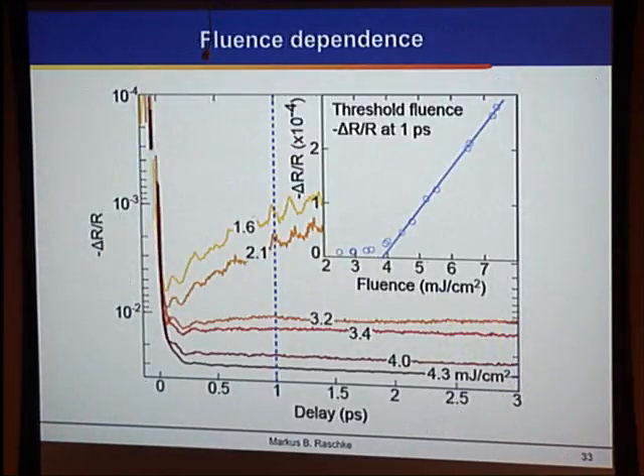So in time-resolved spectroscopy, here looking at the reflectivity change in the far field of these individual single crystals, we see that at low fluence you get a hot carrier excitation and then a coherent phonon emission and carrier relaxation. This is simply what you would also see in a semiconductor. This is a very benign behavior. Distinct is that as you increase the pump fluence, you get a transition into a metastable phase, which is associated with a high pump excitation out of the valence band into the conduction band, and then this band structure collapse. And this is this optically induced metallic phase.